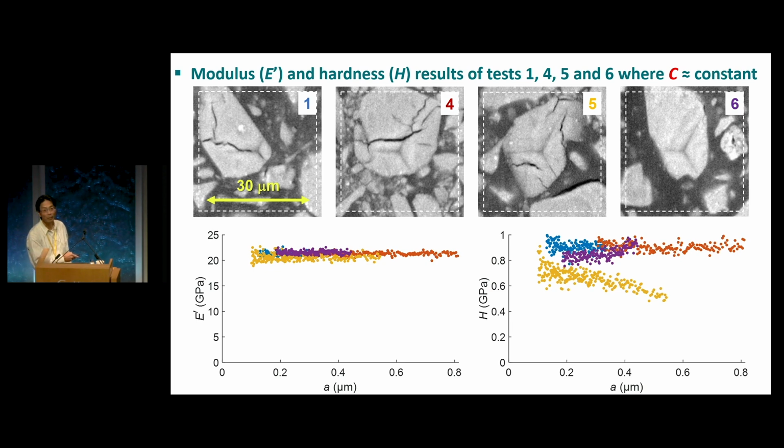And in one case, the effect of the underlying binding material, which is more compliant than the pigment, I think, was playing a role in reducing the effective contact pressure. And getting back to the very initial point, the basis for our model does not assume anything about the hardness, because we know that the hardness, if you are working with such a complex system in the cultural heritage field, cannot always be assumed constant.